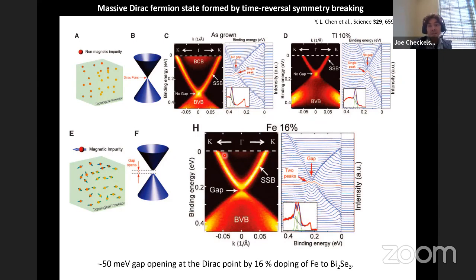So what I can say is that from the perspective of a transport experiment, there is a paper you can find on the arXiv from my previous colleagues, led by Yoshi Tokura and his colleagues, where they grew thin films where they only dope these magnetic ions on one half of the film and not the other. And it really indeed looks like you basically affect one surface and not the other. That is, you can affect the Dirac cone on one surface, but not on the other surface. Spectroscopically, I don't know if that has been demonstrated with the deposition of magnetic ions, but I would imagine that's something that could also be probed. But in this early paper, this was a bulk doping.